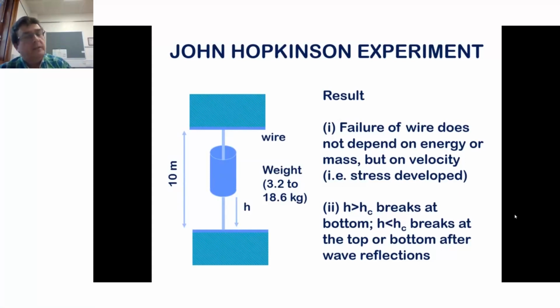And what he discovered in more detail was if he dropped the weight from a very low height, the wire didn't break. Absolutely fine. It's within its elastic limit. It's within its normal strength. If you hit it very hard, it broke instantly, and it broke at the bottom of the wire. But there is a range of energies where the wire breaks at the top or the bottom of the wire. So there is this intermediate range where you cannot say in advance where the failure will occur.